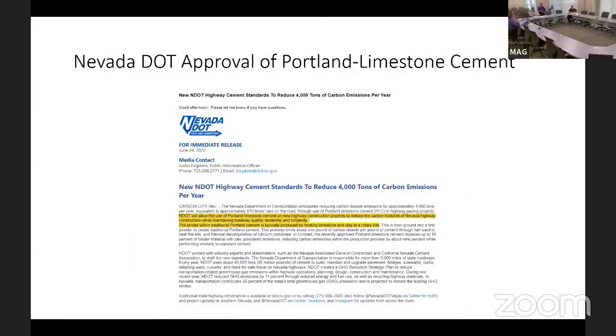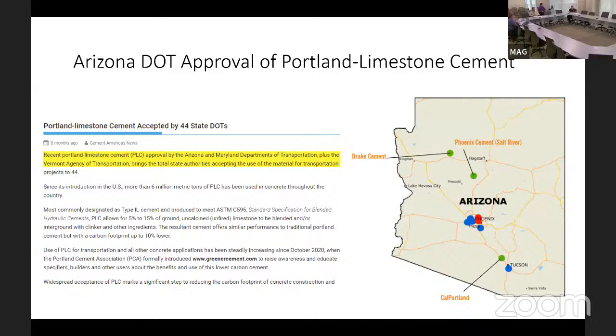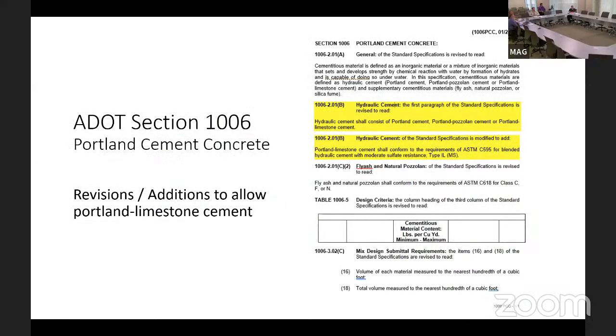Shortly after Caltrans approved, NDOT followed suit and also approved Portland limestone cement. And also shortly after NDOT, ADOT approved. And so ADOT is accepting PLC for all DOT work. And here's a map, shows the geographics of CalPortland, Drake, and SRMG in Arizona. Here's a picture of the ADOT section 1006 Portland cement concrete. You can see the highlighted version there that shows the inclusion now of ASTM C595 IL cement, moderate sulfate. Very similar verbiage that we're asking for MAG to accept today.